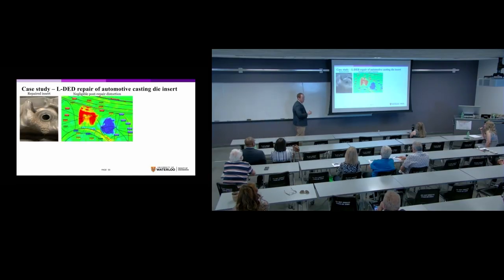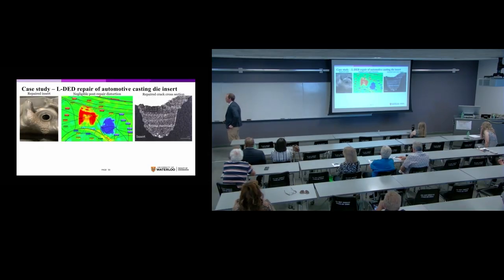We did another laser scan to see if we had any distortion, because of course if we repaired it but we distorted it, then it's not a great process. The good news is we didn't have a lot of distortion, so what we're seeing here is a bit of roughness on the surface. And then we also cross-section it, and here we can see the full repair, and then over here around that is the original part file.